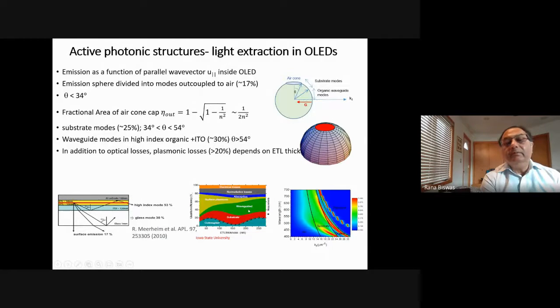So the problem is to get the light out of the structure and to not have these waveguiding modes trapped within. And in addition to the optical losses, there are also plasmonic losses of about 20%. And those do depend on the position of the dipole and its separation from the cathode. So more detailed simulations show you that it depends on the ETL thickness, but in all cases, you can hardly get more than 20% of light out of the structure.